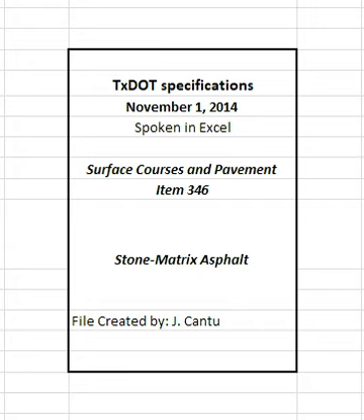Evaluate areas with severe thermal segregation by performing density profiles in accordance with Section 346.4.9.3.3.2, Segregation, Density Profile, DOT. Remove and replace the material in any areas that have both severe thermal segregation and a failing result for segregation, density profile, unless otherwise directed. The sublot in question may receive a production and placement payment adjustment greater than 1.000, if applicable, when the defective material is successfully removed and replaced.